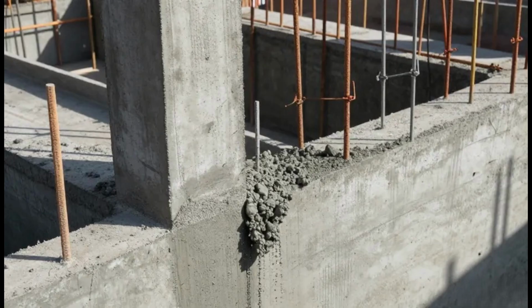They talked briefly about a pour they had done the previous winter, when the temperature had dropped to -12, and they had heated the mixing water to 60 degrees, and covered the finished slab with 2 layers of insulating foam, and then still worried for 3 days until the temperatures rose. That concrete had turned out fine. Most concrete turned out fine when you took appropriate care.